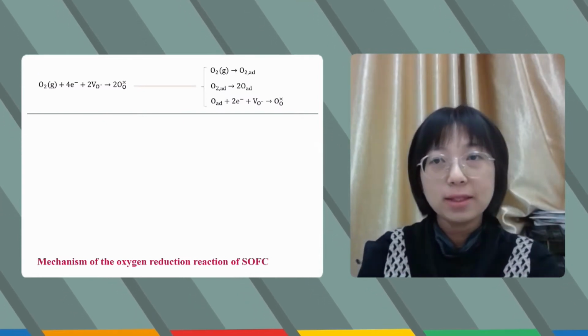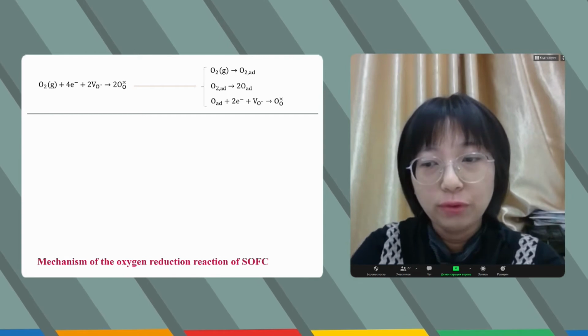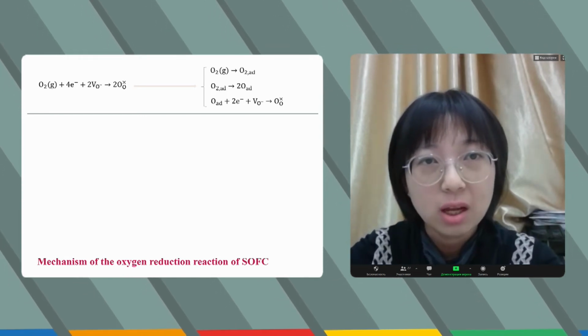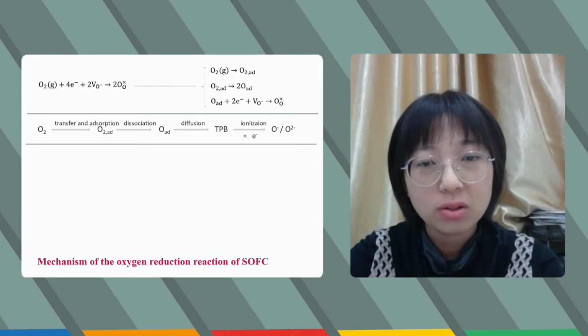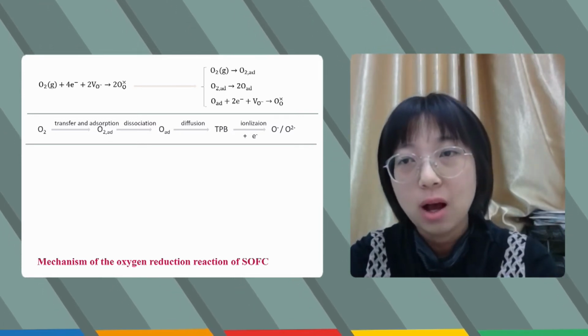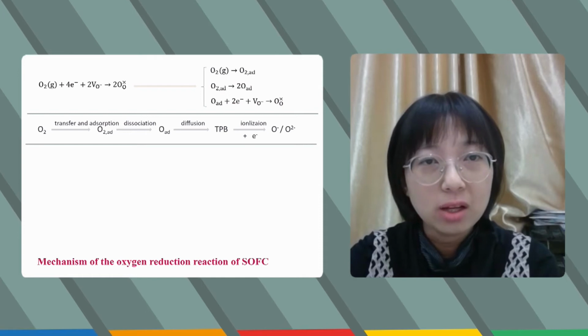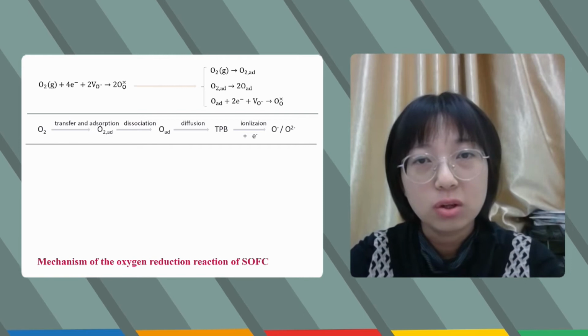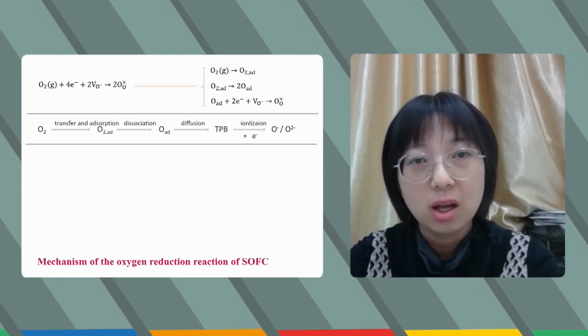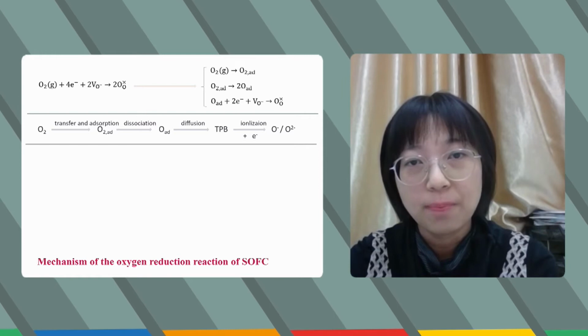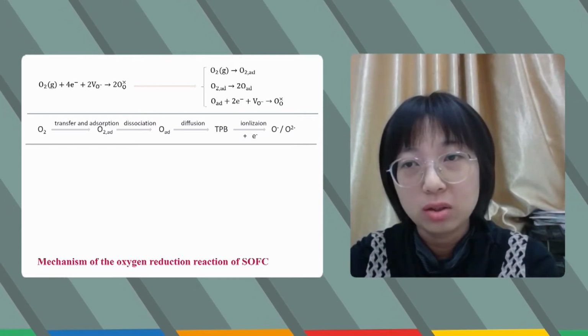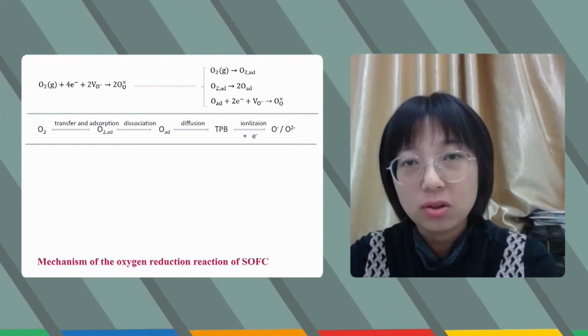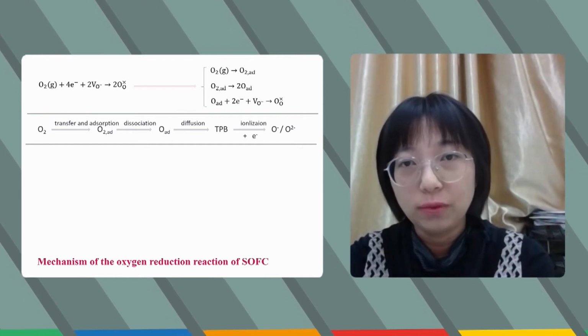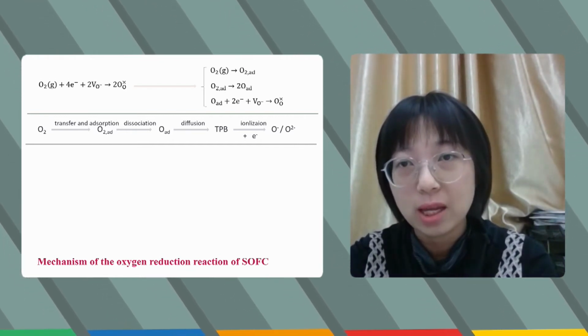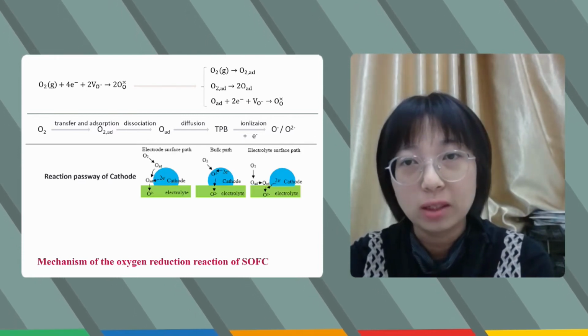To make a promising cathode, we first have to understand the mechanism of the oxygen reduction reaction that happens on the cathode side, as it involves the transfer, adsorption, and dissociation of oxygen into the adsorbed oxygen, which usually needs to diffuse to the triple phase boundary and be further ionized to complete the whole process.